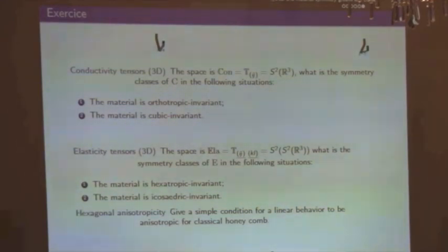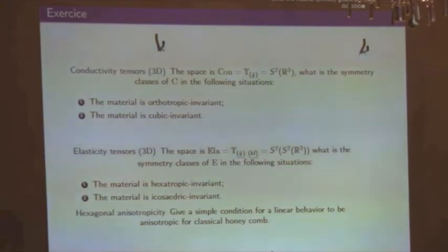But how many planes of symmetry do you have in the icosahedron? You have a lot of planes of symmetry. So if you are transverse isotropic in one plane, by spatial transformation you know that you are transverse isotropic in another plane of symmetry. The only figure that is transverse isotropic in two different planes is the sphere. So by knowing the result in one plane and looking at the Platonic solids, you conclude, without making any computation, that you must be isotropic for icosahedral symmetry.